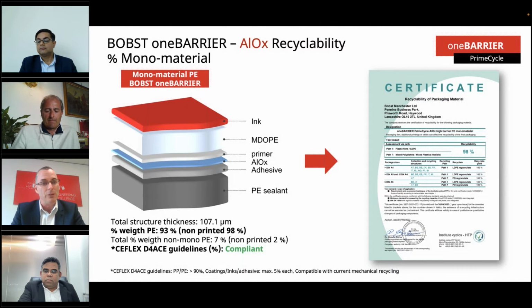And we're proud to say as well, we've obtained this recyclability certification via the Institute cyclos-HTP in Germany, where for the non-printed one barrier PrimeCycle solution, together with the AlOx transparent vacuum layer, we achieved a recyclability level of 98%, which is one of the highest in the market for a high barrier structure. Next slide, Ben.